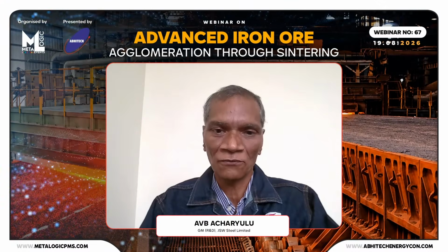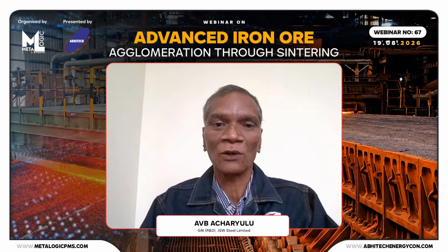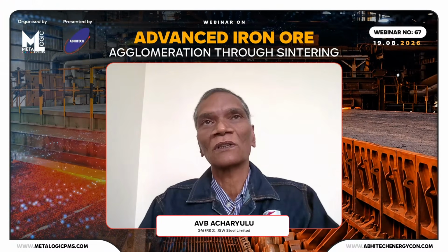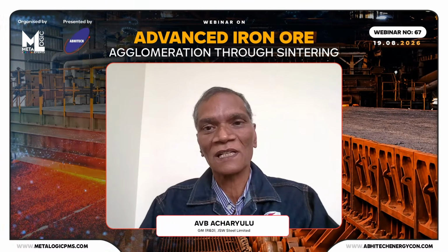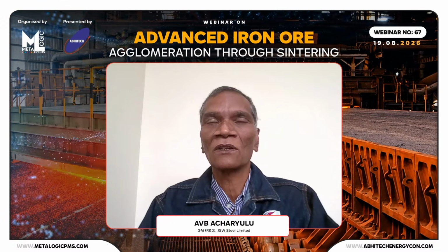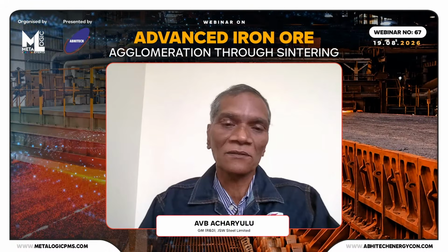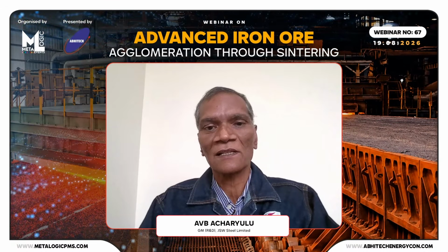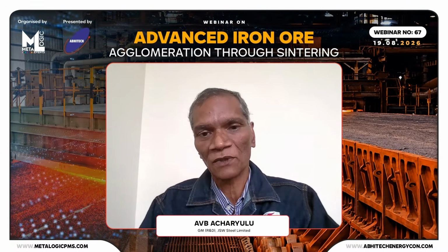For more than 15 years or so, we have been using anthracite as an alternative fuel, which has less footprint than the normal coke fines, because coke has to undergo the carbonization process, which requires a lot of energy. So if you compare anthracite with coke fines, anthracite has an edge over the coke fines.